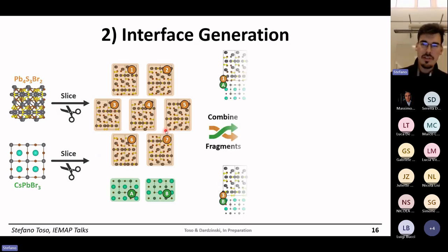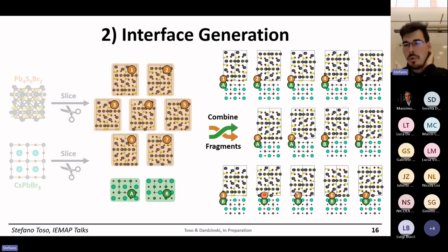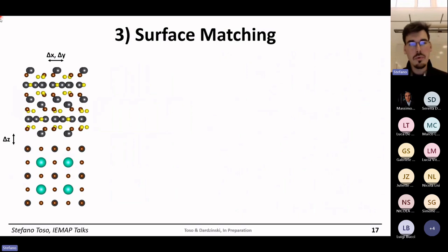And what you do next is that you shuffle these possibilities to construct all possible interfaces for this set of terminations. You have 14 cases in this case. These are not even many. I mean, they can easily grow to 30 or more. And then you have to rank these situations, right? Because one of them will for sure be better than the others, and it will be the favorable one. How do you do it? You take the two fragments of your model, and you try to optimize their relative position. You move them on the side, you move them top and down, and for each position, you construct an energy map.